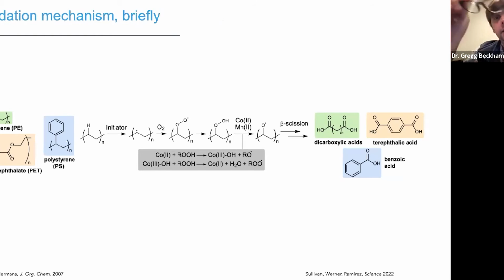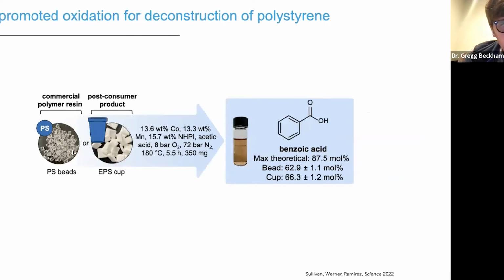And so you have, again, some initiator. It removes a hydrogen atom, you form a radical, which activates oxygen, and then you get these alkoxy radical species that cobalt and manganese can then promote beta fission reactions, and so you can cleave carbon-carbon bonds. And so the idea was, can we cleave carbon-carbon bonds in things like polyethylene and polystyrene, as well as CO bonds in PET. And I'm going to show you very quickly that yes, we can do that.